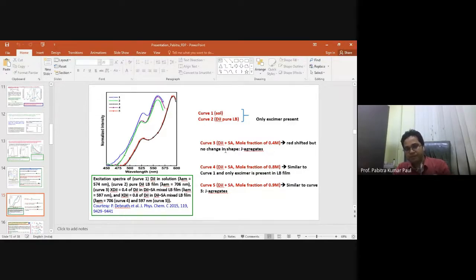And curve 3 and curve 4, you see for curve 3 that it is red shifted, but no change in shape, red shifted but no change in shape. So this is called the J aggregates. This one is the excitation spectrum for mole fraction 0.4, and curve 4 for mole fraction 0.8, it is very similar to curve 1.